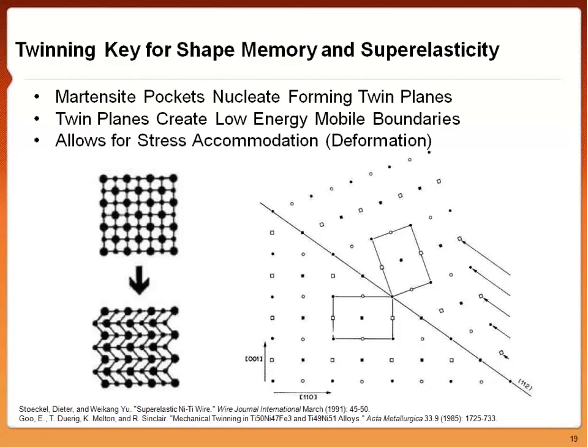Then when we move from austenite to martensite, we create this zigzag structure at the bottom. If we just take a line and draw it through the middle over here, we see that what we create is a mirror image plane, or in crystallography, a twin plane. Basically, the top portion of this structure is a mirror image of that on the bottom. When pockets of martensite nucleate within the austenite structure, you create twin planes. As these new structures are forming all over and combining together, they'll crash together and form a mirror plane between the two.